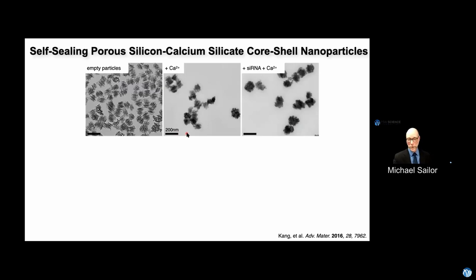So I've shown a lot of cartoons, not a whole lot of real data. On the left here, these are what our little silicon nanoparticles look like when we start, before we load a drug in them. If we just throw them into a calcium chloride solution at the right pH, you can see the spongy pores we see in our original particles seem to go away. And in fact, that is the case. The pores get sealed up, but they don't change size. They don't turn into a concrete sidewalk. It just cements locally because the silicon is local to the nanoparticle. So the chemistry really focuses just on the nanoparticle.